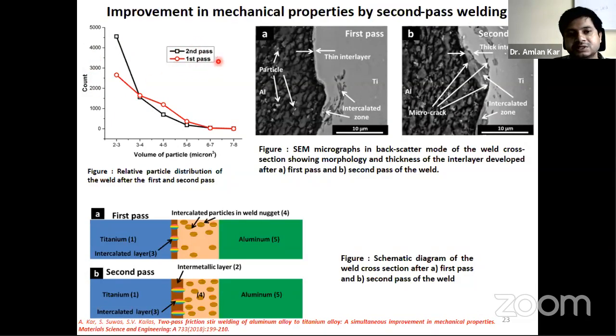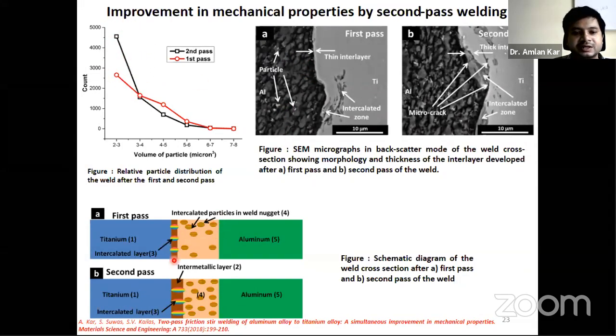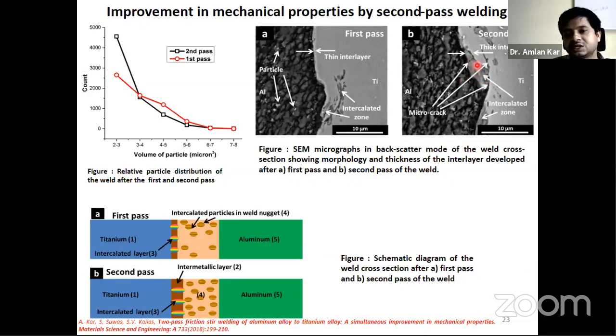As you have done the second pass on top of the first pass, we can see very high fractions of fine particles, and they actually distribute in the weld nugget. Depending on the microstructure, we can see there is a very fine intercalated structure, and there is a very thick layer of intercalated structure, and there is a higher fraction of deformation. From here you can see it in the weld nugget.